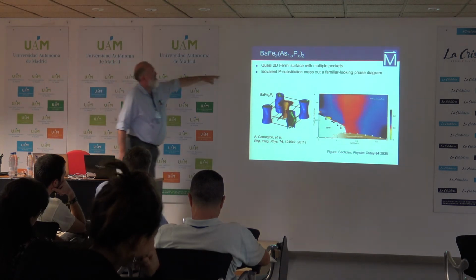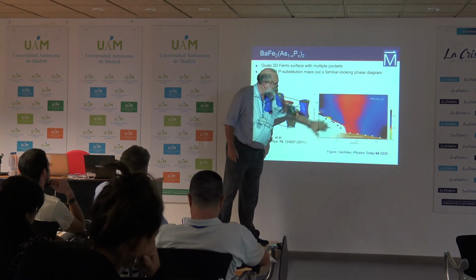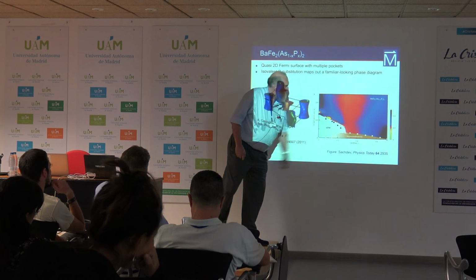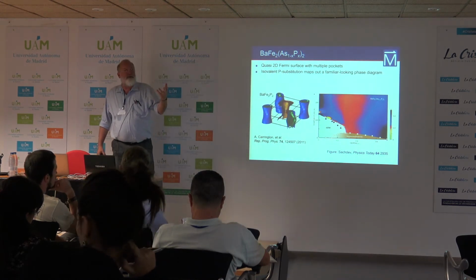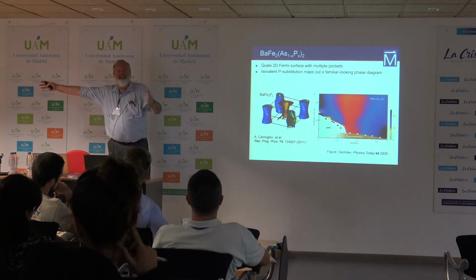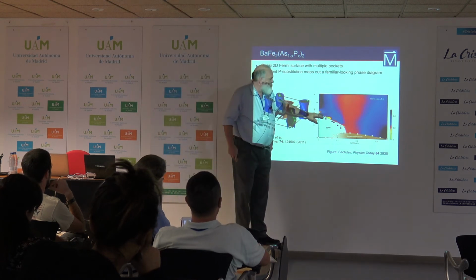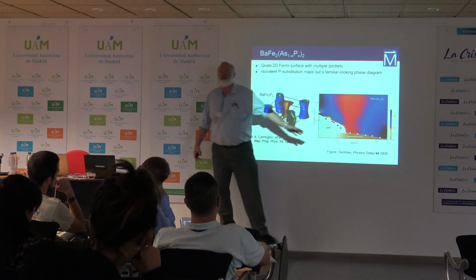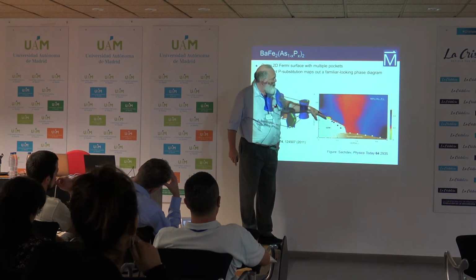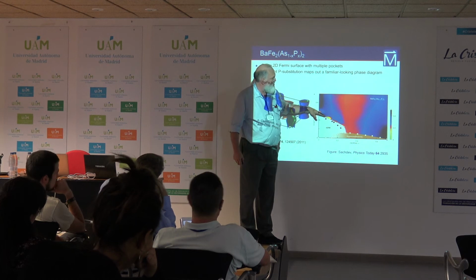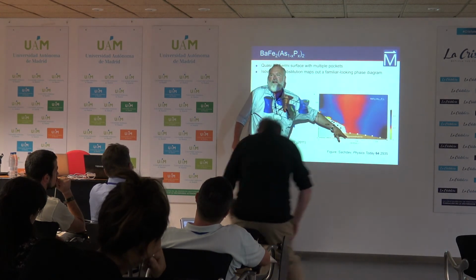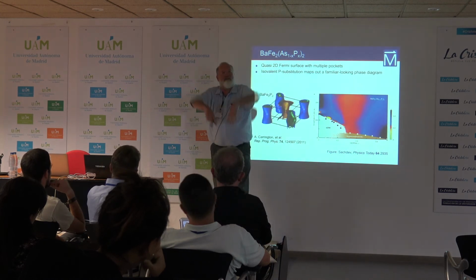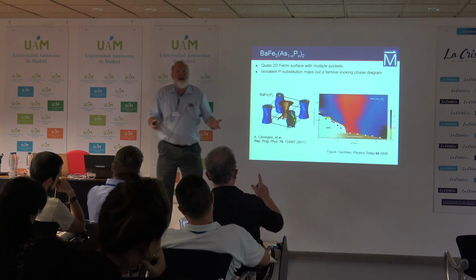And the isovalent phosphorus substitution maps out a familiar looking phase diagram with the spin density wave phase that's crashing to 0 right where Tc is optimum. And I don't want people who don't have the decades of perspective to lose sight of the fact that when it was first seen, so many systems had magnetism crashing down at the top of a superconducting dome. This was a sea change. This is the only logical way to find a new superconductor. Find a magnetic system, tune some thermodynamic parameter like doping or pressure. If the magnetic phase transition is dropping, go to the point where it goes to 0, and you're likely as not to see superconductivity. The only other way to find superconductors is to put several elements into a mortar and pestle, grind them up, bake them, and then put contacts on and measure.